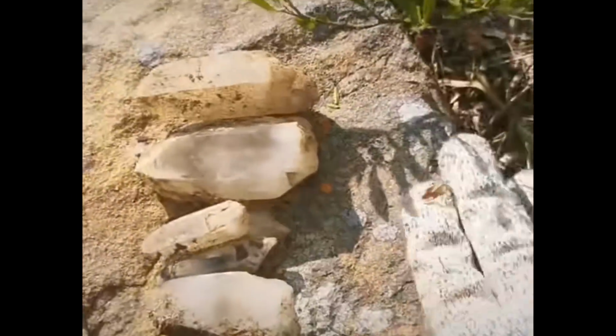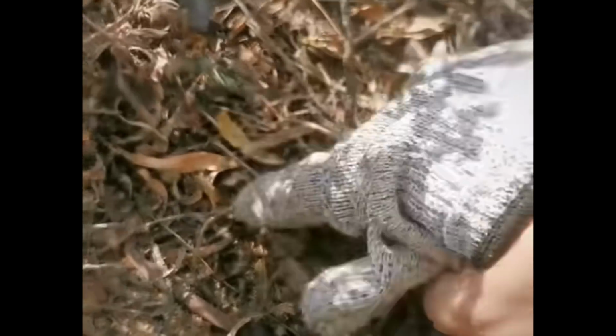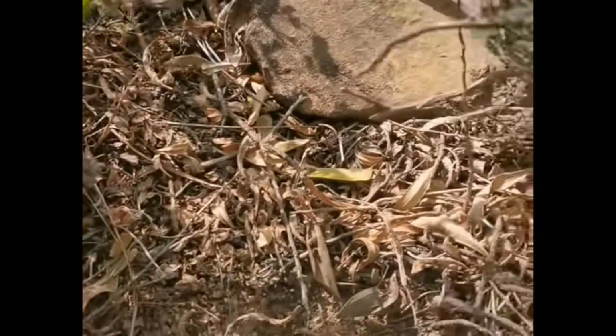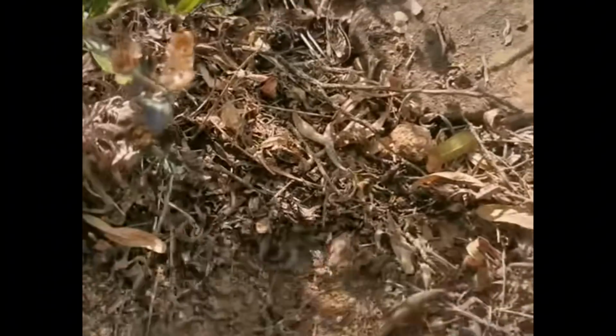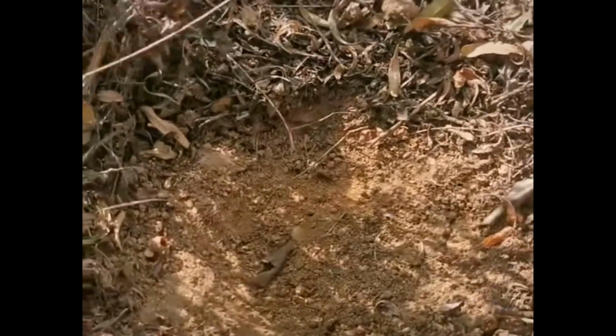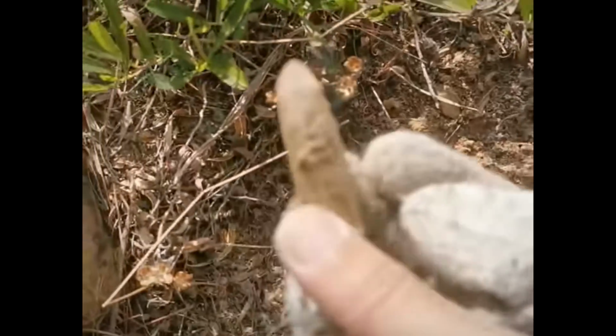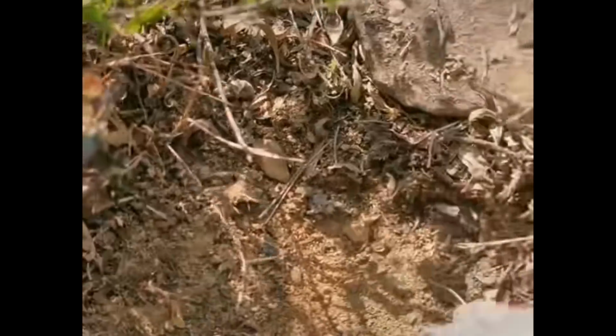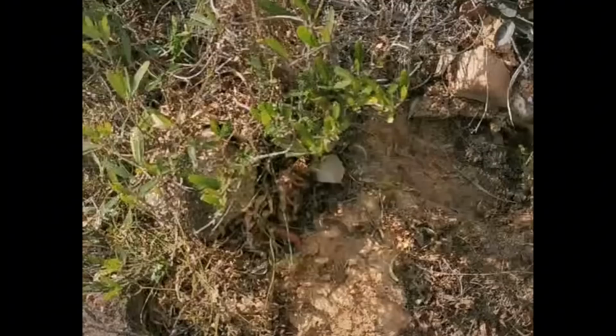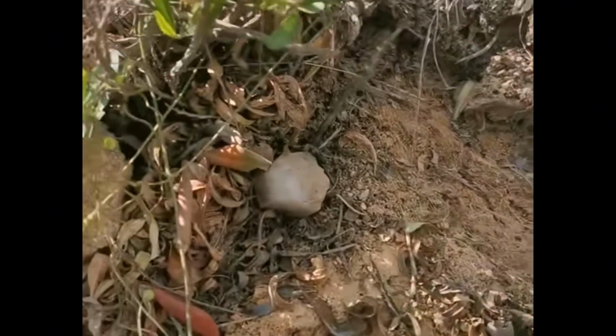Opal presents a different challenge. Found in volcanic and sedimentary terrains, like the Andamooka fields in Australia or the Virgin Valley in Nevada, common opal potch can appear glassy, colorless, and oddly lustrous. It may show play of color or not. Because it's hydrated silica, its weight can vary, and it often registers poorly on thermal conductivity, but just well enough to confuse a rush test. Unlike diamond, opal often shows internal crazing or moisture loss fractures, and under UV, it can fluoresce in whites, greens, or oranges, depending on impurities.